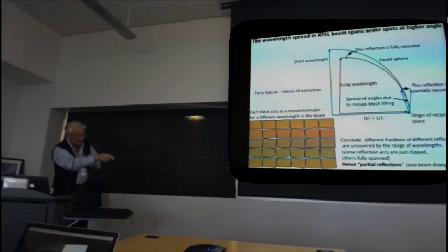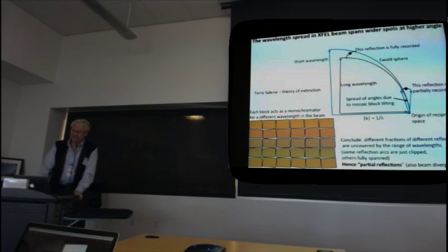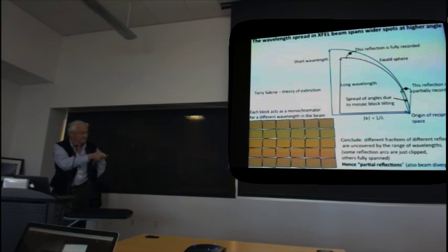If I now impose on that my Ewald sphere, you can see that because of the different wavelengths, the thickness of the Ewald sphere increases with scattering angle, and it'll span perhaps a full range of this spherical cap up here, but much less of it down here. That's going to produce an error, because we're only measuring part of the angular distribution of this Bragg reflection, but we're measuring all of this one.